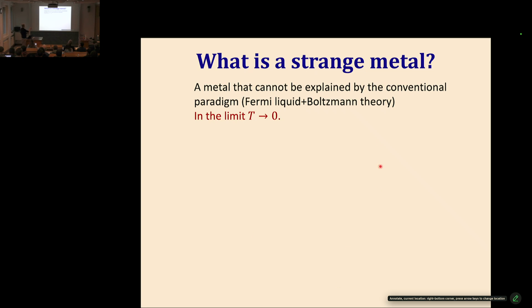So we have a metallic system whose properties we cannot explain using the conventional theory, Fermi liquid plus Boltzmann theory, in the limit T goes to 0. Remember, Fermi liquid theory is an effective low energy theory. So if we want to make sharp statements about whether something behaves like a Fermi liquid or not, we should always, at least in principle, take the limit of asymptotically low energies. Of course, in practice, that means go to the lowest available temperature and find a behavior which cannot be described within Fermi liquid theory. And now, why is that interesting?